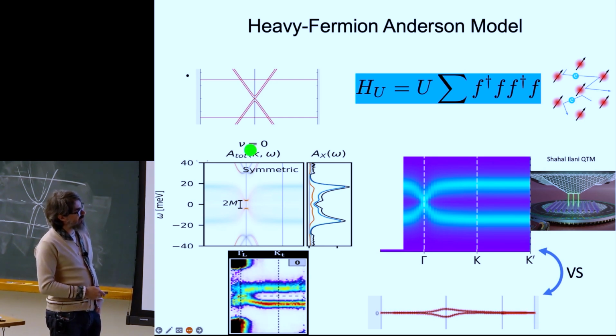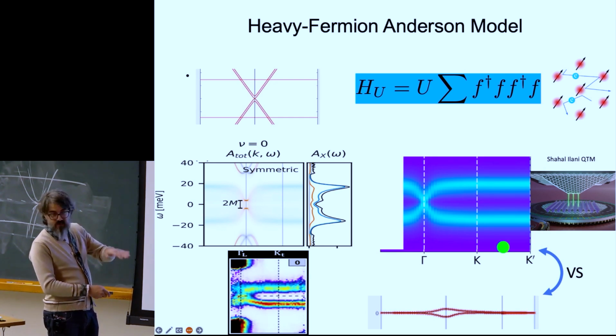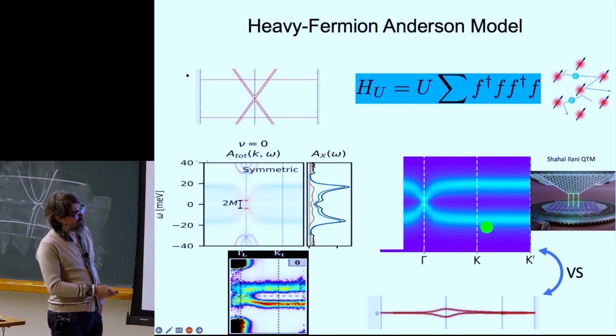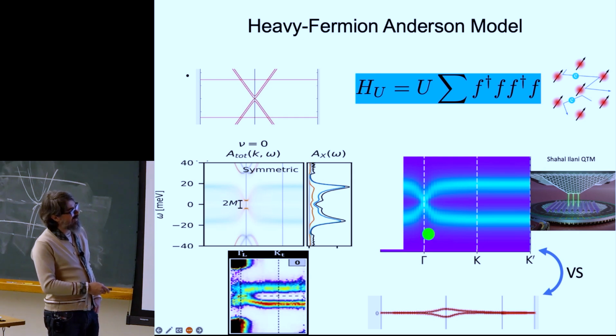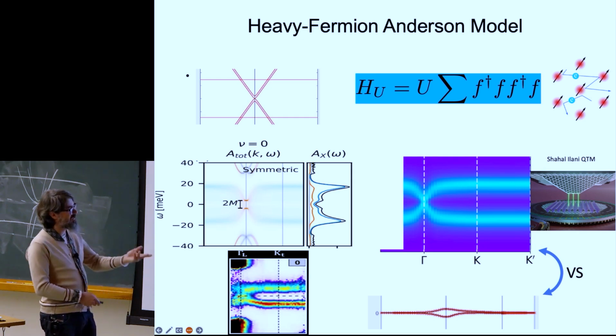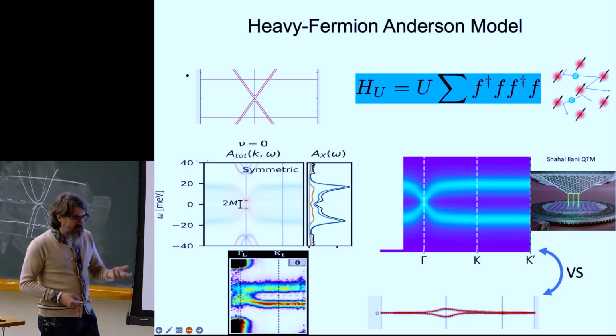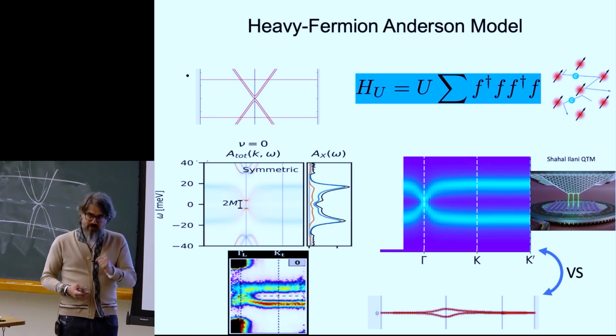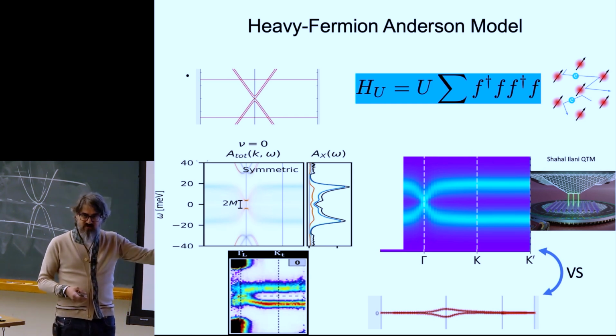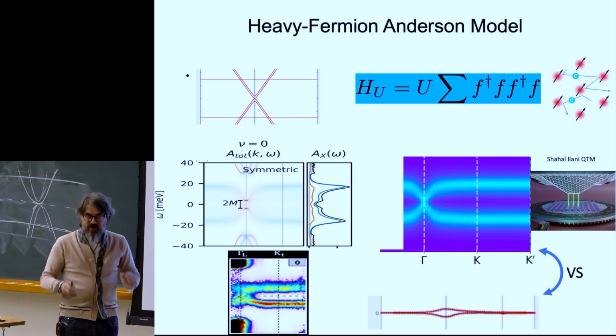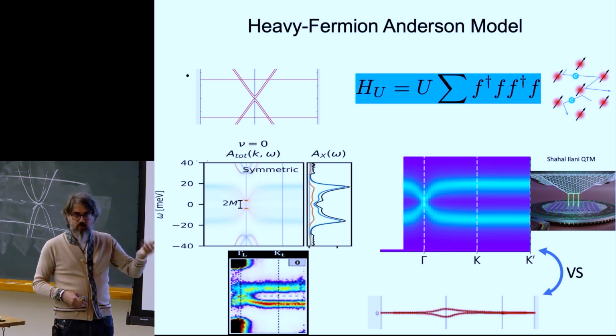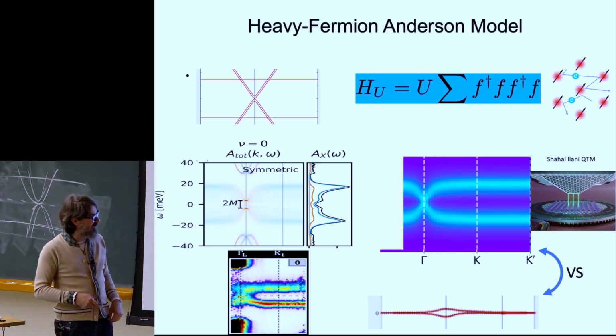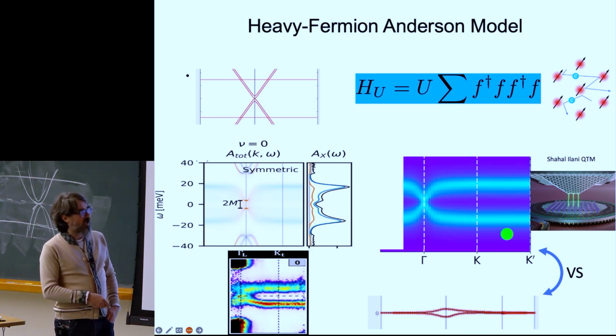Whereas this spectral function, just because the F electrons have now split by an interacting effect, is gapped at the K point by a large gap of the order Hubbard-U, gapless at the gamma point. So exactly the opposite of this. So now what does this say? This says that if you build two samples, one at angle 1.5 degrees where you don't have flat bands, and one at angle 1.05 degrees where you have these flat bands and the interaction, the spectral function of one of them should look like this. At large angle, i.e. non-interacting, and at small angle it should look like this.